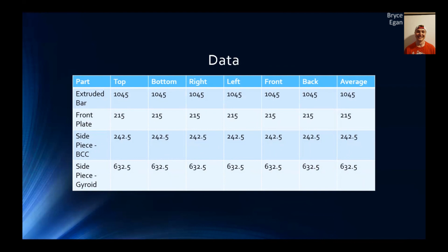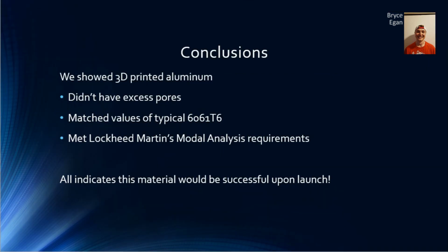Since each part has a fundamental frequency above the target value of 100 Hz, we can conclude with a high degree of confidence that the finished product would resist the pitfalls of resonance during launch. In conclusion, we showed that 3D printed aluminum does not possess an excess of pores, strength values match those of typical 6061 T6, and that our printed parts met Lockheed Martin's modal analysis requirements. This indicates that aluminum printed via a selective laser melting process can be a suitable material for flight-ready parts.